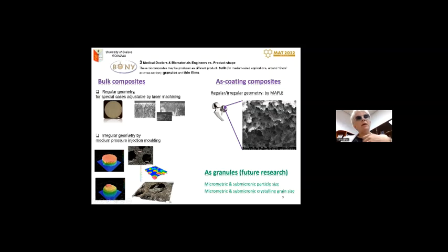But most of the time, you may need an irregular geometry of the alloplastic graft, because the bone defect is not always regular in geometry. So we developed another route, medium pressure injection molding of these materials, and we demonstrated that we can obtain nice structures, isotropic and also anisotropic, from the same mixture of nanometric hydroxyapatite and micronic titanium hydride. Also, the colleagues from another institute, from the lasers institute in Bucharest, obtained nice coatings of these biocomposites on the titanium substrate by the MAPLE technique. So we can develop this kind of product.